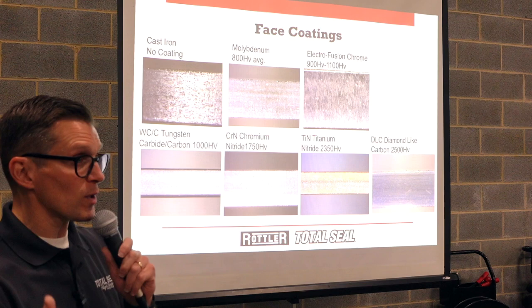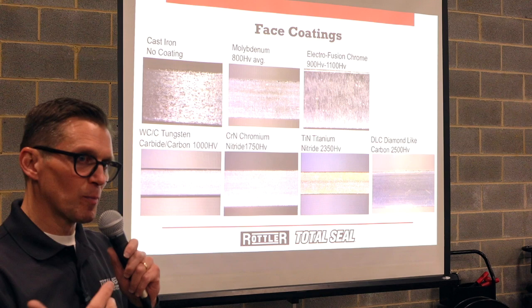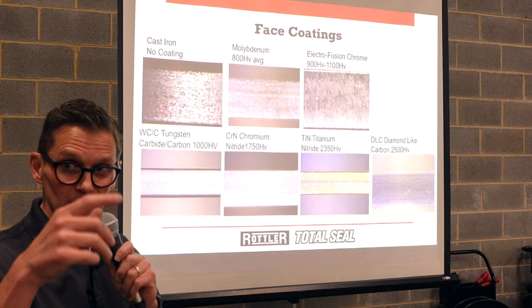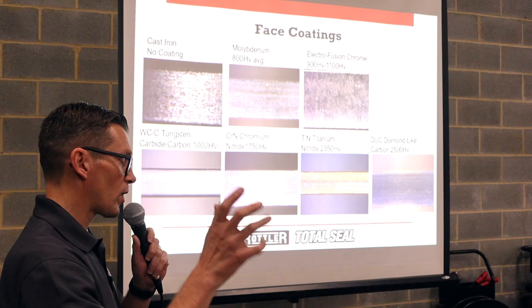Well, then we got chrome. Chrome's really hard, super durable. But the trick is, it's like a chrome bumper. It's plated, it's dipped, so it's got lumps and bumps. You ever put together an engine with some high-tension oil rings, and the oil rings obviously are chrome-faced, and you see streaking in the bore up and down when you put it together? Those are the high spots from the chrome. Once it wears in a little bit, it all goes away, because those high spots in the chrome are breaking in.